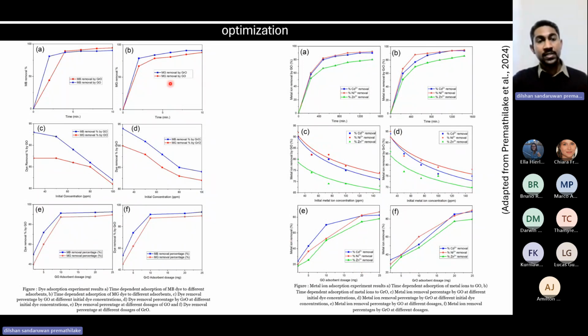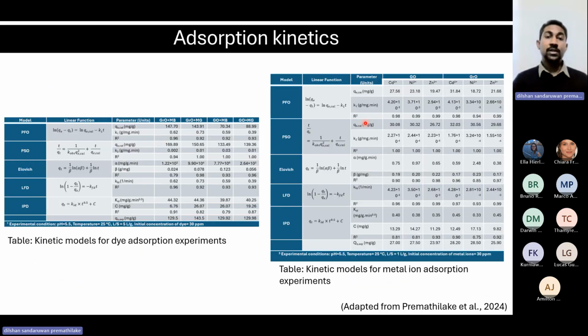In both cases, you can see that the adsorption time or the kinetics are very fast. I could remove somewhere around 90 to 95% of pollutants from the wastewater within 10 minutes. However, for the metal ions, it took around 24 hours to reach the maximum adsorption limit. And then I used these results for the adsorption kinetics evaluation.